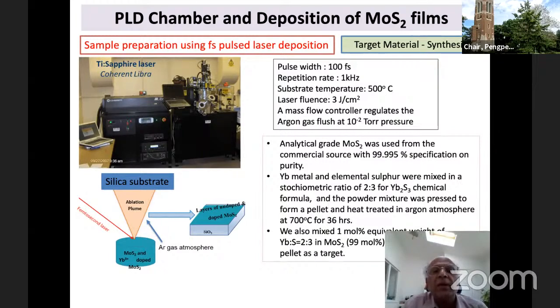The parameters of the pulse laser are 100 femtoseconds, 1 kilohertz. Deposition temperature is 500 degrees centigrade. Laser fluence is 3 joules per centimeter square. And we regulate the pressure inside the chamber. The target materials we use are undoped MoS2 and ytterbium-doped MoS2, which we synthesize by heat treatment techniques.